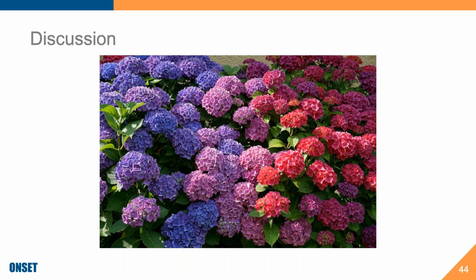Good question, Josh. How does the solution recondition the probe? It does that by rehydrating. It's a really cool dynamic between the internal and external gel layers, and that is they have a specific ion concentration in those tiny, tiny microscopic layers, and the internal electrolyte has a specific salt content, and the storage solution has a specific salt content as well. So what it does is it reconditions those layers to have the right amount of ion concentrations that it's pulling from those salt concentrations. So that's how it reconditions it.